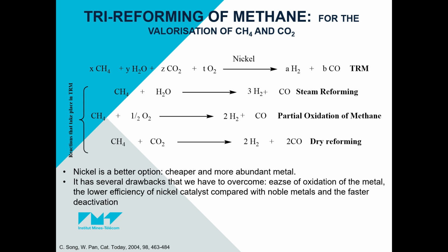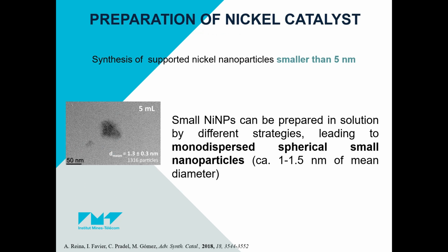Our approach for overcoming these drawbacks will be the preparation of nickel-based catalyst with a small active site. Lately, in the literature, it has been reported that the small active sites present better activity and lower deactivation. Consequently, our idea is to prepare small and well-dispersed nickel nanoparticles under 5 nanometers.